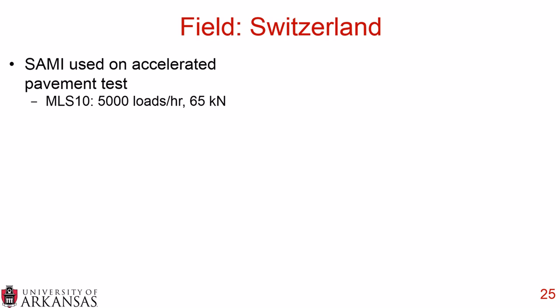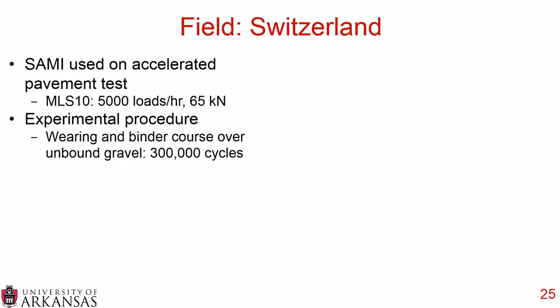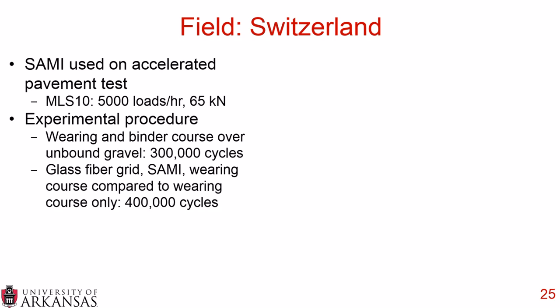Now, moving over to Switzerland, they used different SAMI mixtures on an accelerated pavement test. They used an MLS 10, which applied 5,000 loads per hour at 65 kilonewtons. And what they did, this is a very interesting study. I enjoyed reading this paper tremendously. They placed a wearing and a binder course over unbound gravel, and they applied 300,000 cycles of the MLS 10 to that pavement. Then they placed glass fiber grid, SAMI, and a wearing course to that existing deteriorated pavement and applied 400,000 cycles. So they deteriorated a pavement in the lab, and then they placed this glass fiber grid and SAMI combination and saw what it did after that was placed.